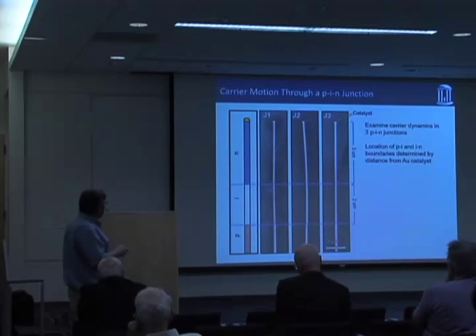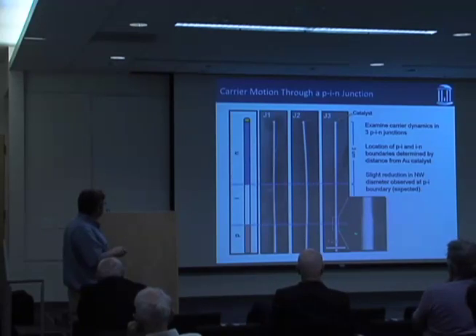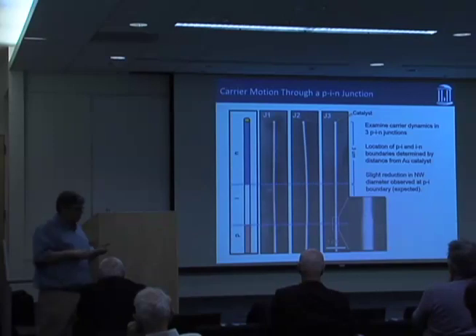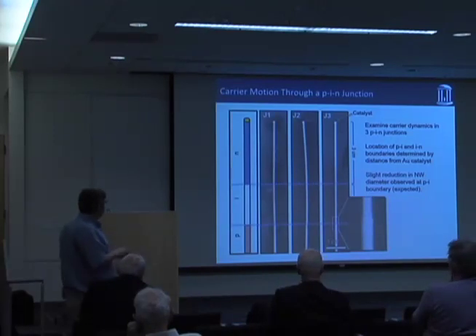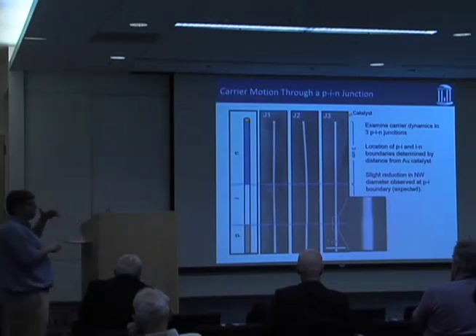When you look at the SEM micrographs, you don't know where the doping is. But there is a slight change in the diameter at the interface between the P-type and the I-type, which has to do with the way the growth changes. Jim's group understands this, and we were able to see it in the SEMs, and they were exactly where we thought they were going to be. So we're fairly confident we know where the junctions are, or where the boundaries are between the different materials.